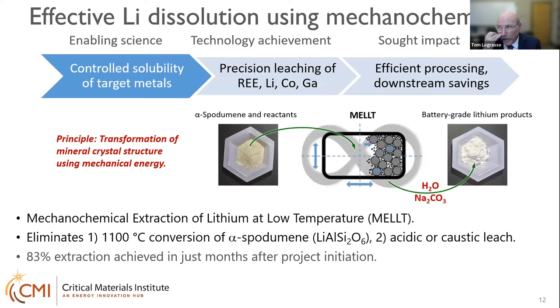Coming back to the hard rock, the United States has a number of spodumene hard rock deposits in the southeast of the country, Tennessee, North Carolina. The technical gap there is you have to take the rock and roast it in order for the lithium mineral to be leachable. So we've taken an approach that allows for room temperature extraction, a conversion through mechanochemical means, to take the spodumene and transform it from the low temperature alpha spodumene to a leachable form that usually requires this 1100 degrees heat treatment.